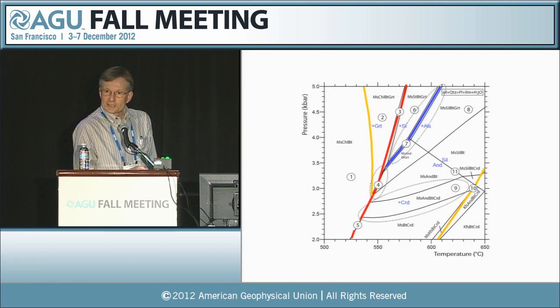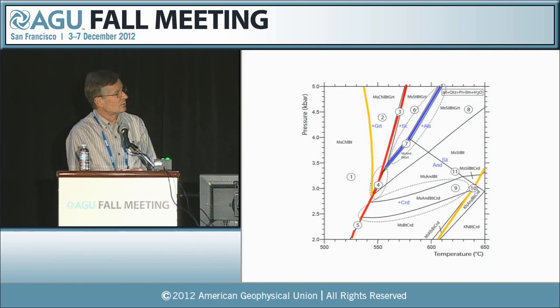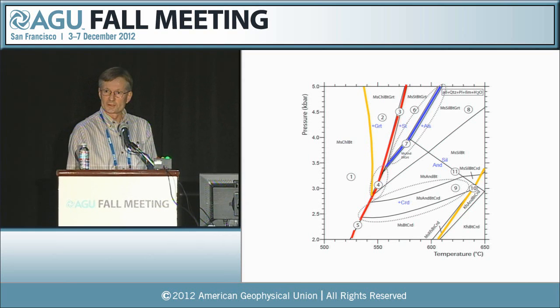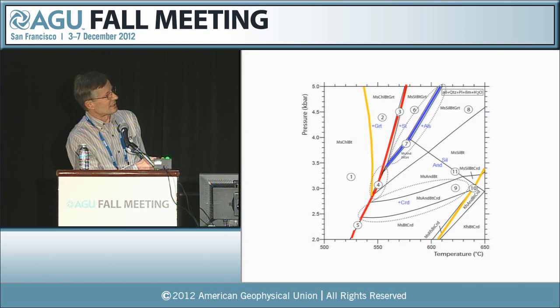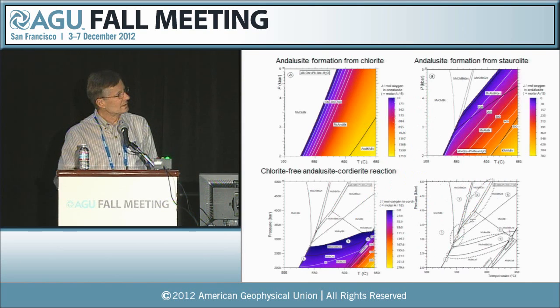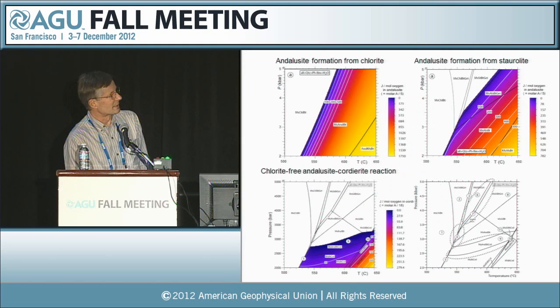So the next thing you can do is actually make reaction affinity maps, which show graphically the amount of overstepping, or rather the rate of buildup of reaction affinity, which allows you to predict the amount of overstepping. I've shown 3 examples here, or I'm choosing 3 examples. This is the chlorite to andalusite reaction. This is the staurolite to andalusite reaction, actually just down here. And this is the andalusite to cordierite reaction. And these are kind of the extremes. And these are the reaction affinity maps.